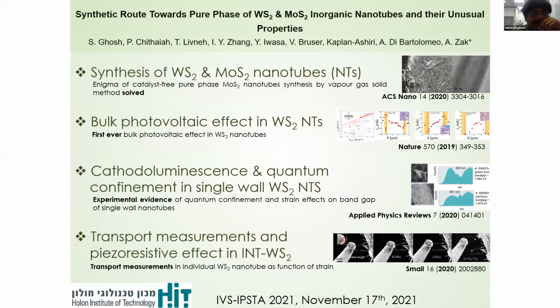Thank you, Professor. Ever since the discovery of tungsten disulfide and molybdenum disulfide nanotubes about 3 decades ago, they have been accepted as functional materials in different labs among researchers. Here in our lab, we are really focusing on the growth mechanisms of these nanotubes. Regarding the tungsten disulfide tubes, we have precise control on their growth, their crystallinity, and their structures. So we can produce these nanotubes, around 10 microns long and 80 nanometers wide, in grams per week.